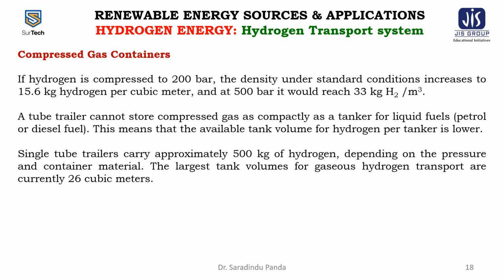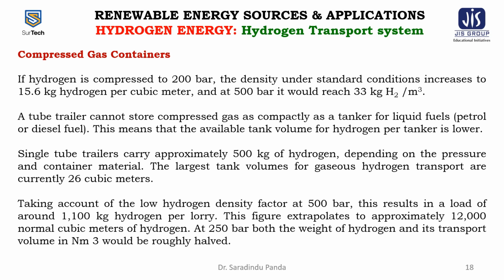Single tube trailers carry approximately 500 kg of hydrogen depending on the pressure and container material. The largest tank volumes for gaseous hydrogen transport are currently 26 cubic meters. Taking account of the low hydrogen density at 500 bar, this results in a load of around 1100 kg hydrogen per lorry. This figure extrapolates to approximately 12,000 normal cubic meters of hydrogen. At 250 bar, both the weight of the hydrogen and its transport volume in normal cubic meters would be roughly halved.